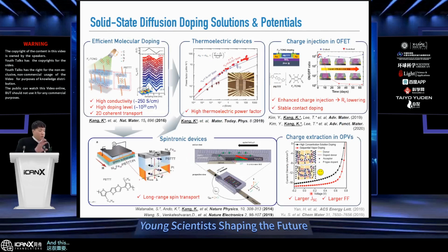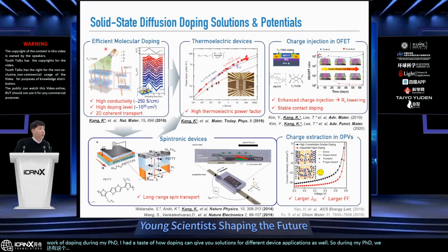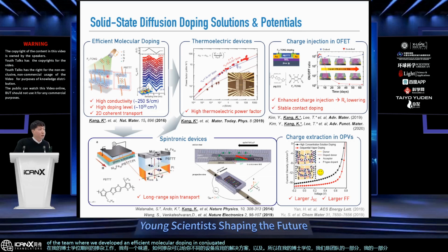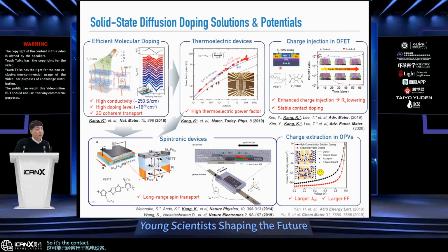And with this work on doping during my PhD, I had a taste of how doping can give you solutions for different device applications as well. I was part of the team where we developed an efficient molecular doping in conjugated polymers. And that actually resulted in a highly conductive and high doping level, efficient doping method. And that could be applied to thermoelectric devices, as well as the contact doping in organic FETs.